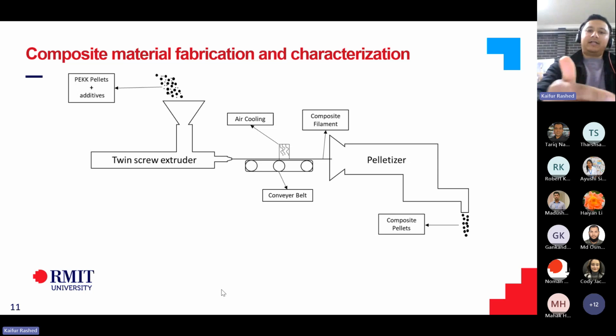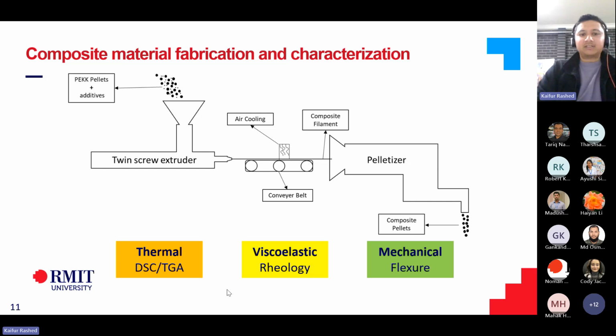The twin screw extruder was used mainly to give a good mix between the polymer and the additives, and then I pelletized that, and I used those pellets to test them. I performed thermal analysis using DSC and TGA. I studied the rheology as well, because in additive manufacturing, rheology is very important. You need to know the viscosity, and you need to know that whatever composite you're manufacturing will be able to be printed as well. That's where rheology comes in. And I also tested their mechanical properties, to give us an idea of whether we are improving their mechanical properties or not.